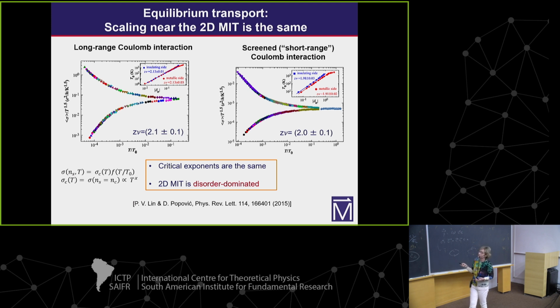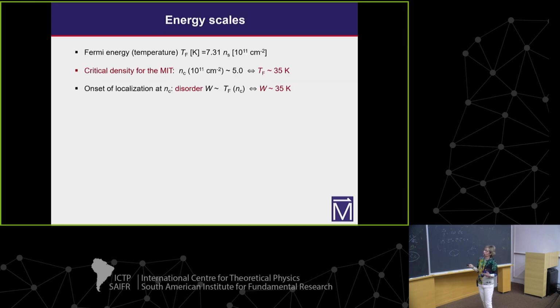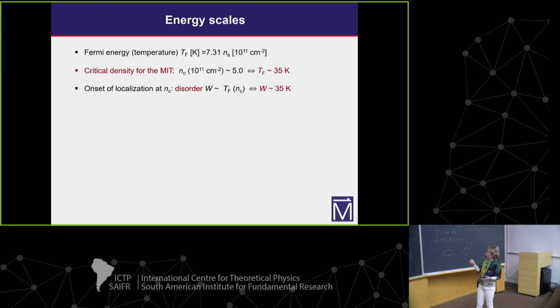So far the equilibrium transport looks the same, and before I move on to non-equilibrium dynamics, let me just mention what the typical energy scales are. Around the critical density for the metal insulator transition, the Fermi energy and disorder are about 35 Kelvin.